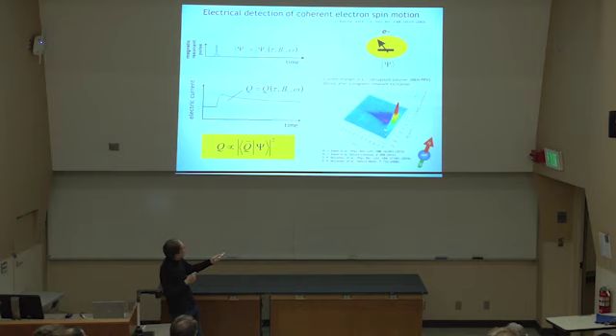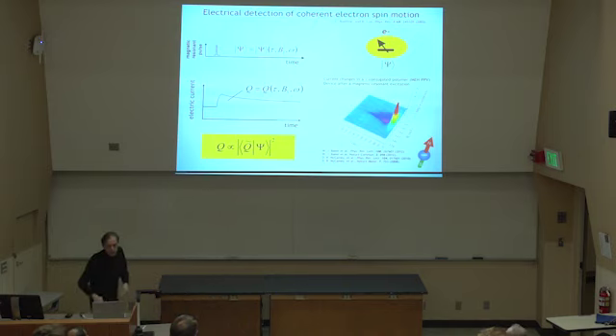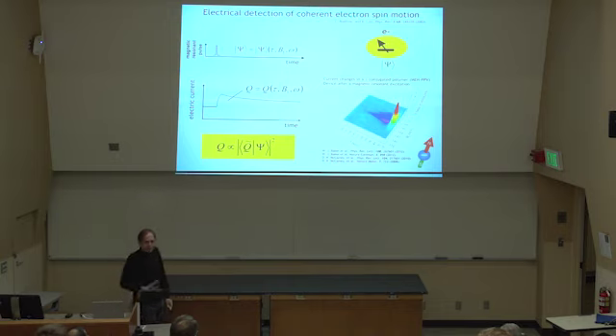The change in current as a function of time and applied magnetic field if you produce a one pulse excitation that's X band, that is around 10 gigahertz, at the time t0. And that means an instantaneous one, meaning one whose length is short to that time scale. And what you see is a response at a particular magnetic field, and then you record this, you count your charge carriers, and now my claim is, well, I do a coherent spin measurement. How do I know that?